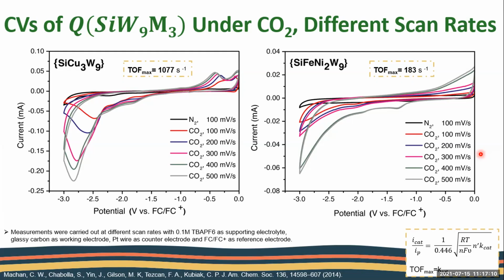What is important here, when we measure CV for that, you can see that when we add carbon dioxide to the complex, we immediately see increasing current. That means that we have catalytic current, which indicates that we have catalysis here. The same is also seen in the iron nickel complex. When we calculated the turnover frequency from the CVs, according to the known equation of theoretical turnover frequency, we got 1077 second minus 1 turnover frequency for copper 3, compared with a lower turnover frequency for iron nickel 2, equal to 183.